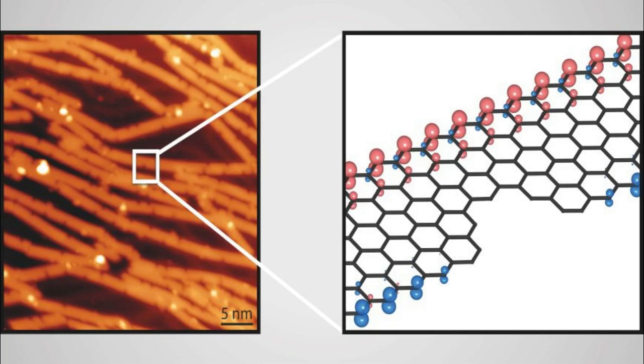The effect of these bite defects on the electronic structure and quantum transport properties of 6ZGNRs is again examined theoretically. They find that the introduction of the defect, similarly to AGNRs, causes a significant disruption of the conductance. Furthermore, in this nanostructure, these unintentional defects induce sublattice and spin imbalance, causing a local magnetic moment. This, in turn, gives rise to spin polarized charge transport that makes defective zigzag nanoribbons optimally suited for applications in all-carbon logic spintronics in the ultimate limit of scalability.